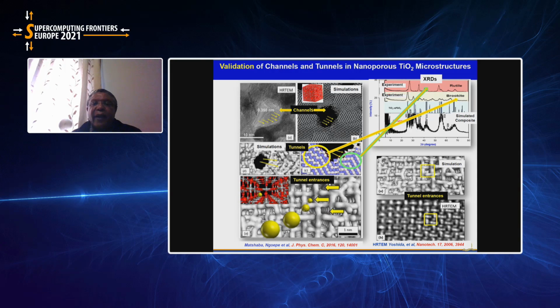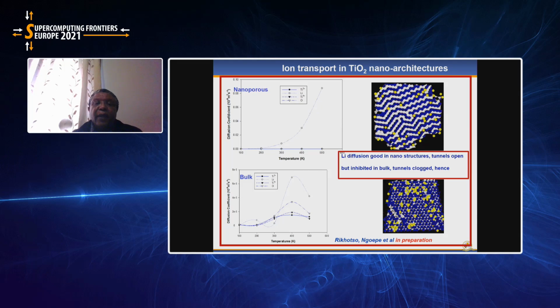And here we have simulated the entrances through which the lithium, which is in yellow, can move into the material. But on the right-hand side here, we have a pattern of entrances which is found by simulations, which is very, very close in pattern to the high-resolution transmission electron microscope. So in this way, we are able to model these complex microstructures.